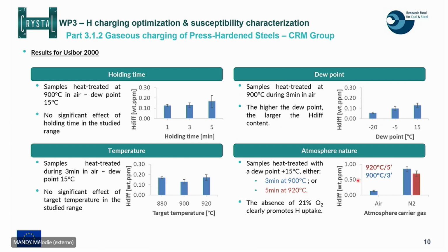Below, you see the effect of the atmosphere. So here we made two tests between air and nitrogen, and we see that there is really a strong impact. When we work with nitrogen atmosphere, we have diffusible hydrogen contents which can be really larger. This is typically something that is not at all used industrially, but it was interesting in the framework of this project in order to enhance hydrogen uptake and to reach, I would say, extreme conditions in this case.